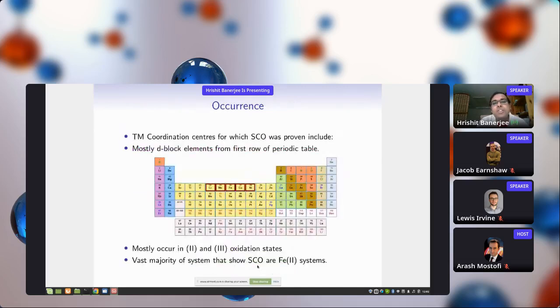But let's see in which materials this happens. The transition metal coordination centers for which SCO was seen are basically the first row of the d-block elements, so chromium, manganese, iron, cobalt, and nickel. And they mostly occur in 2+ and 3+ oxidation states, and the vast majority of these systems that show spin crossover are basically iron 2 systems.